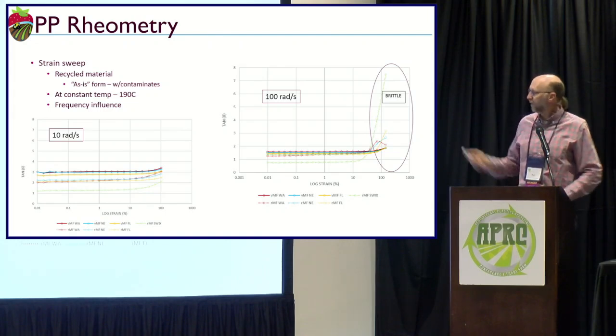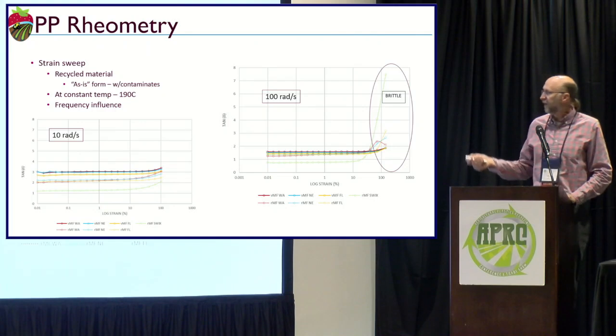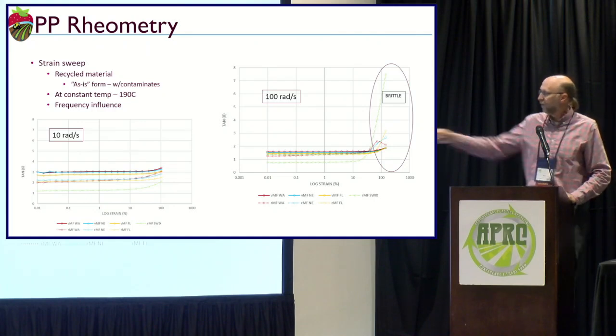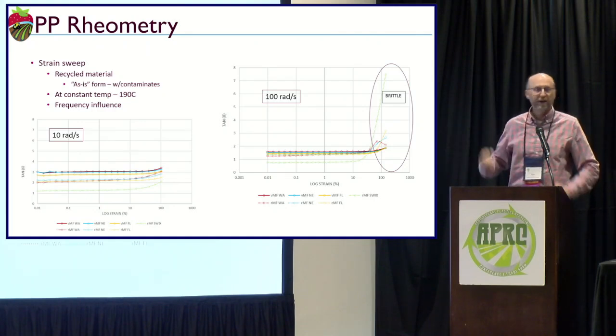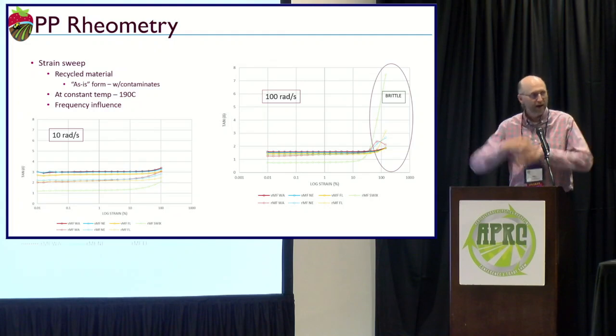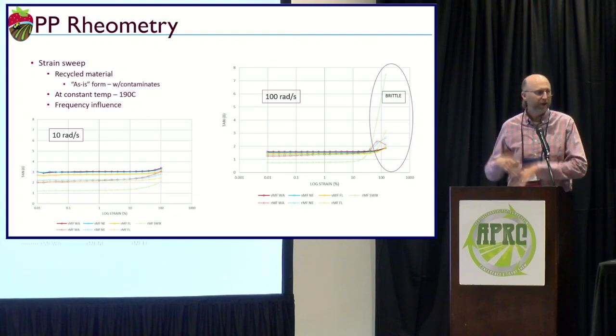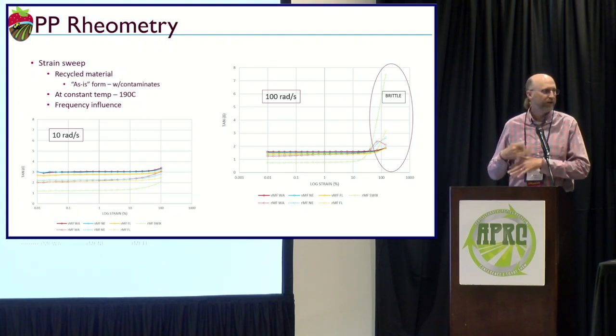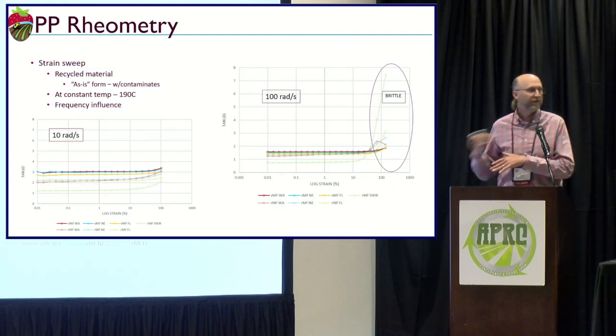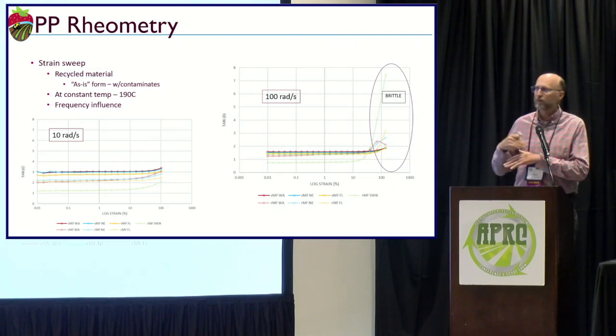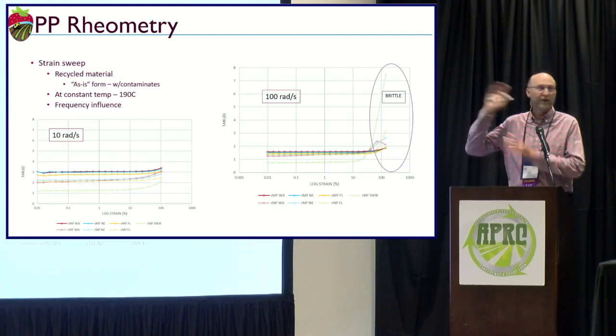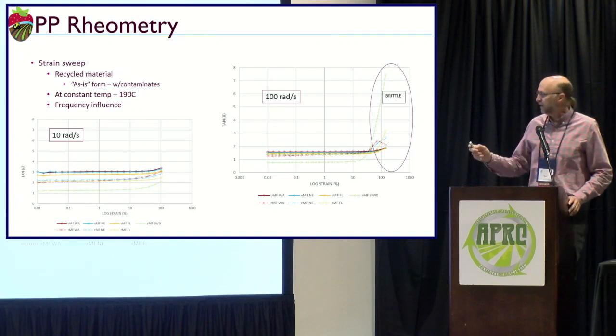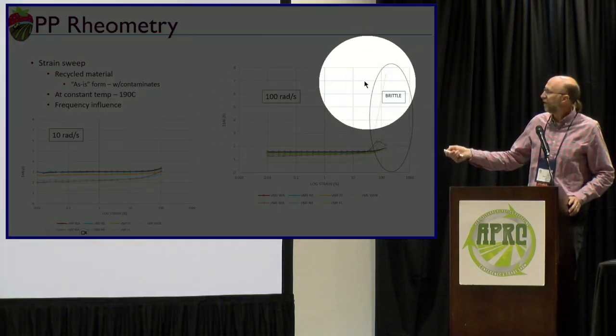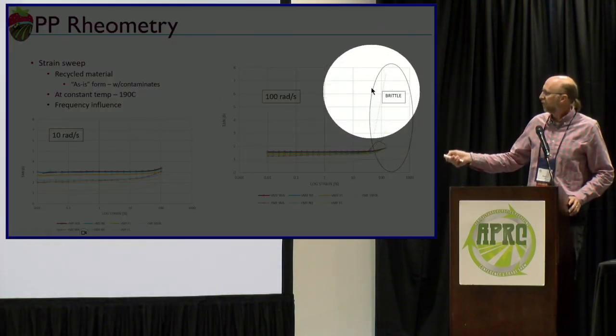And this thing, what we're seeing with this is that once you go to higher rads per second, higher speed at a really high displacement, that's when you start to see things change. You start to see things go away from a linear viscoelastic property into this nonlinear chaos that's going on. And you can see in this right here, this green dotted line is really getting out there.